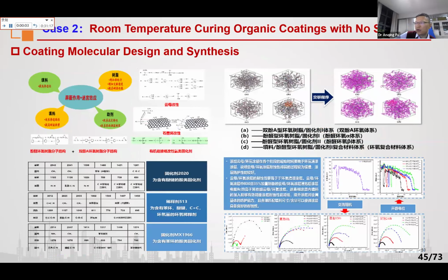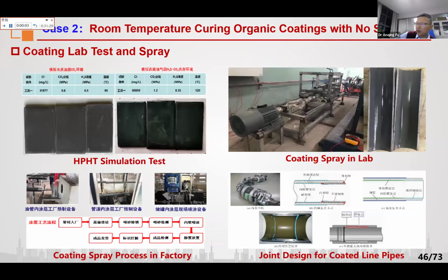This slide shows how we do molecular design and synthesize the epoxy coating. The coating we developed can endure 35 megapascal CO2 and 2 megapascal H2S under the temperature as high as 130 degrees C. Besides the paint itself, the spray process or the technology, as well as the joint connection, are very important for the coating application in field, no matter for the tubing, casing, and the pipeline, and the tanks, vessels.